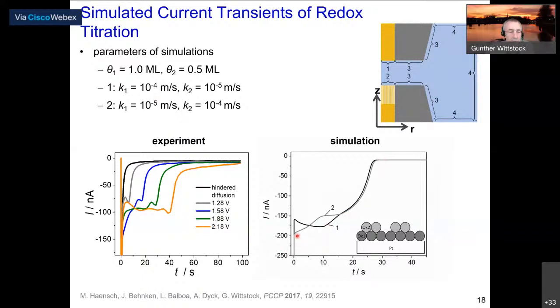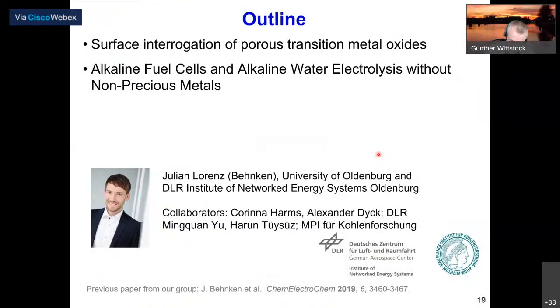The opposite is true if we exchange the rate constants: then we start with a higher current, then it falls off to the next plateau, and then finally falls off immediately. And we will see later on that this effect is more pronounced with other materials than for surface gold oxides. And that is work on which we would now like to go to more interesting catalysts like transition metal oxides, which can be used for alkaline fuel cells and alkaline water electrolysis without using precious metals.